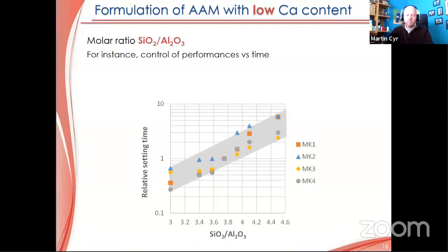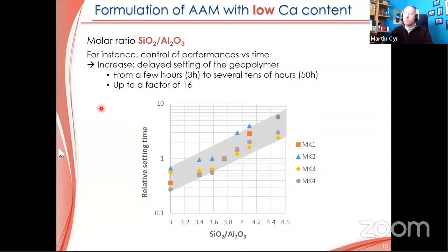And when we have a look at these ratios, take for instance the ratio silicon over aluminum, it can control a lot of things, meaning that they are very useful when you understand how to use them. You can control the performance versus time. I'm just showing here the relative setting time against this ratio, silicon over aluminum, for four different metakaolin. And what we can see is that we can delay the setting of the material itself from a few hours.